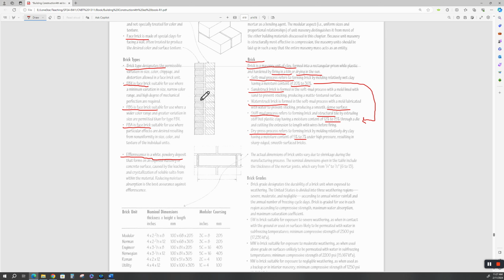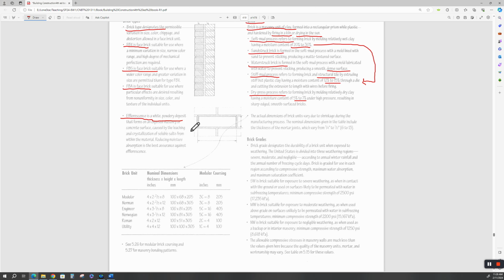Let's say that you wanted a nice, what did Acme call that red? I think it was East Texas, North Texas red, high fired brick clay. Yeah, it was like a brownish red. And let's say you wanted that look on your building. If you're not careful with the efflorescence, then you'll get these white streaks appearing on your brick, and you'll have to go out there and pressure wash it or etch it or acid wash it with a very, very mild solution to try to get that efflorescence off. So you spend all the time and money to build this thing and to spec a good, pretty brick, and if you're not careful with the moisture content in the mortar, you'll start leaching efflorescent lines, little white streaks.